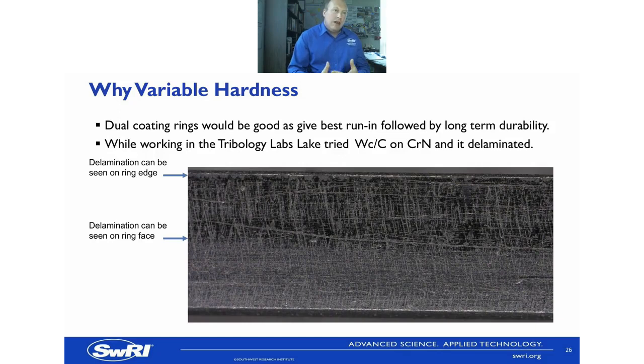One of the things that Lake tried while he was working in the labs with us was a WC/C on a CrN, and it delaminated. You can see on the top edge there where it's beginning to delaminate, and a few spots on the main ring where it's touching. That delamination is not good. It works against exactly what you're trying to achieve, because you then have small particles in the oil that are going to get between the ring and the liner and create those scores that are exactly what you're trying to not have and get rid of.